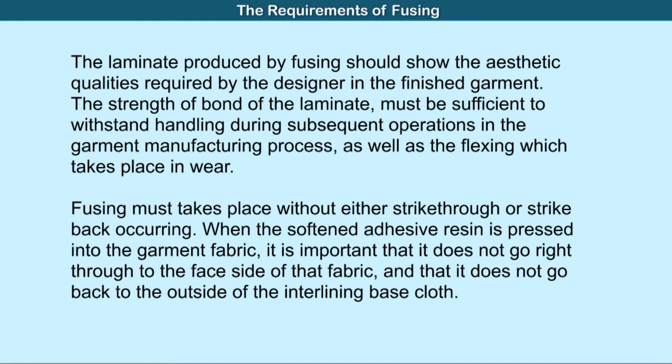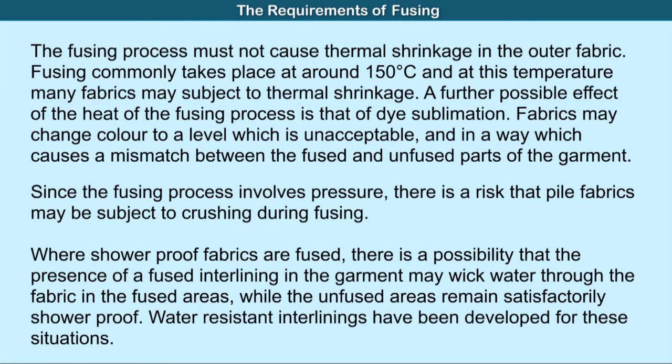Fusing must take place without either strike through or strike back occurring. When the softened adhesive resin is pressed into the garment fabric, it is important that it does not go right through to the face side of that fabric, and that it does not go back to the outside of the interlining base cloth. The fusing process must not cause thermal shrinkage in the outer fabric.